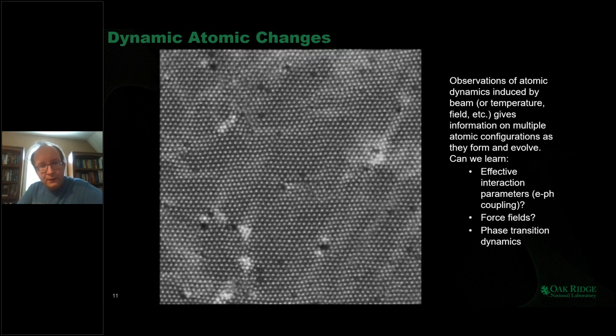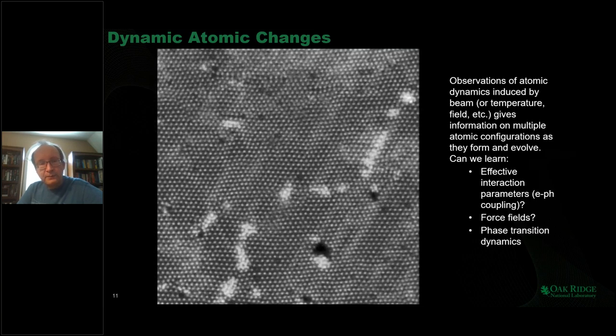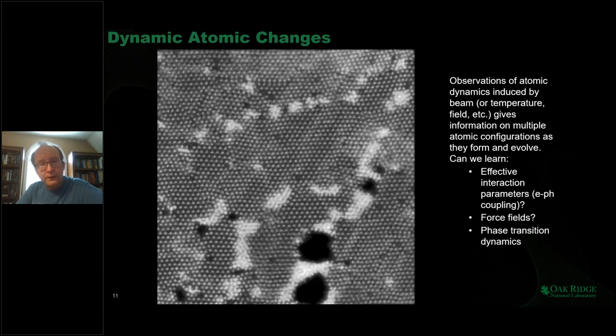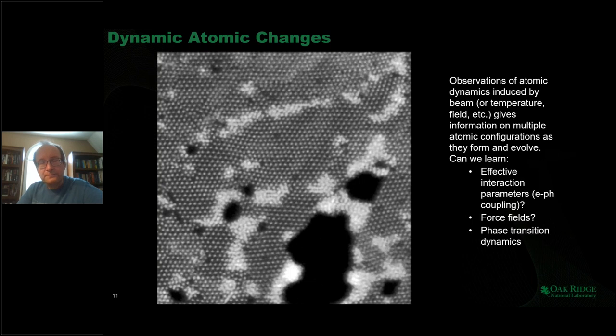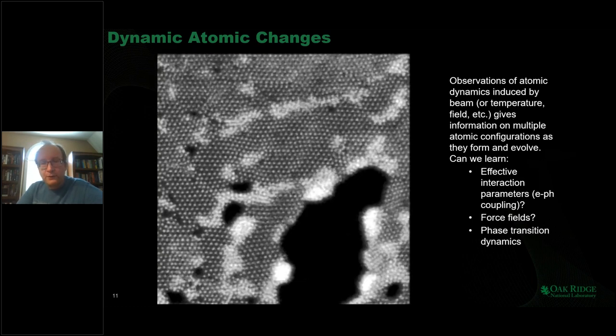Now imagine that I keep looking at this sample in the microscope for a few minutes. What you see happening is that the material starts to fall apart under the action of the electron beam. And from the point of view of the electron microscopist, this is a bad thing. We just deal with an unstable material where we see a big degradation. So therefore, what we need is to either reduce the dose or reduce the voltage of our probe to minimize the damage.